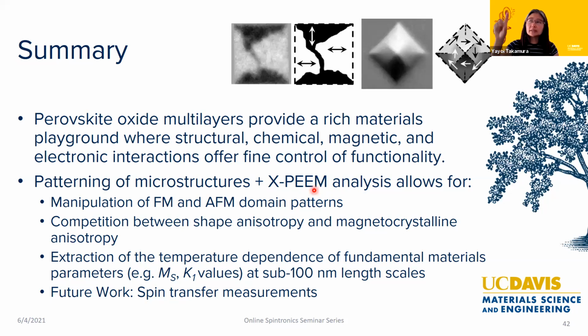But if you are just in that region where you have those structures, you would get a convolution of the top layer and the bottom layer. And so if they're doing something completely different, then it might be really confusing as to what the magnetic structure is. The lateral resolution: there's the resolution at which you can actually see that something exists, right? So that's always the SEM resolution.